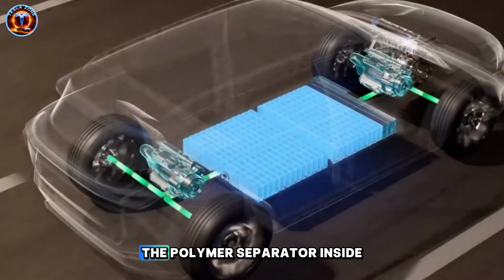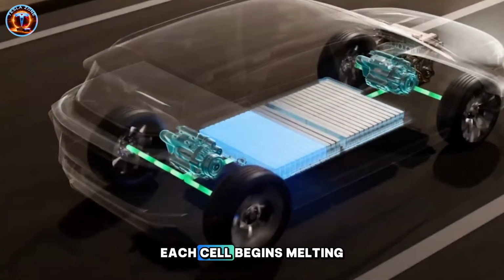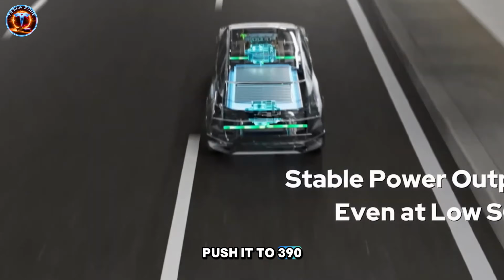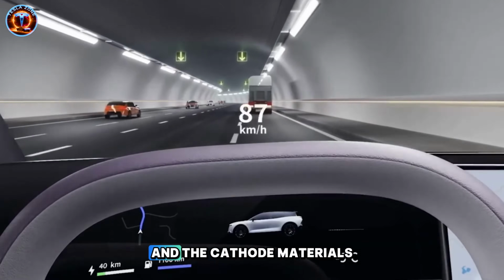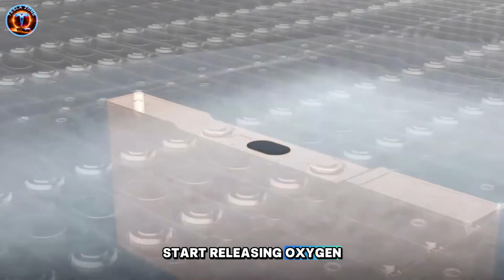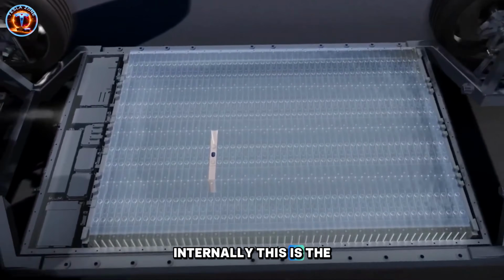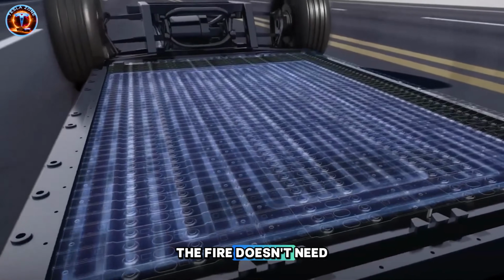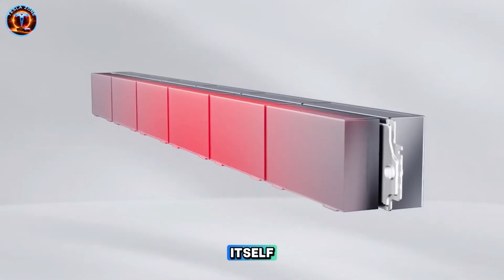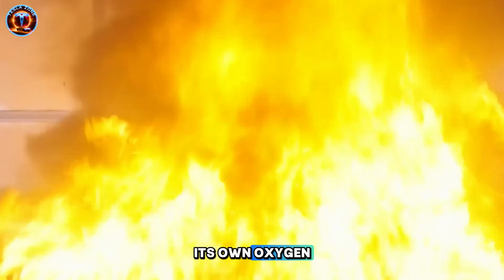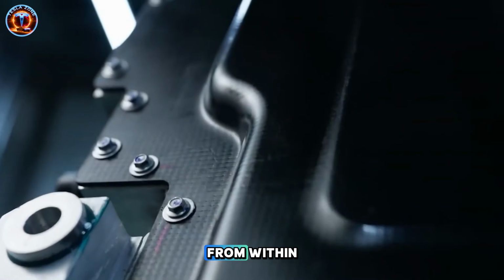At 360 degrees Fahrenheit, the polymer separator inside each cell begins melting. Push it to 390 degrees, and the cathode materials start releasing oxygen internally. This is the critical point. The fire doesn't need outside air to sustain itself. The battery is generating its own oxygen, feeding its own combustion from within.